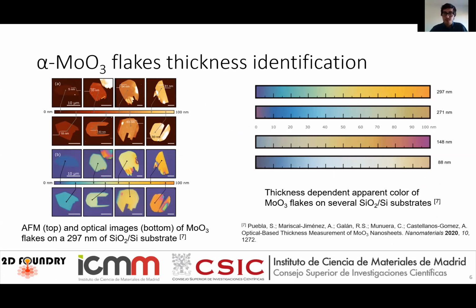We see these experiments as interesting enough to develop some methods to calculate the thickness and to speed up the thickness identification and the symmetry identification of the crystal. For example, we have placed molybdenum trioxide flakes onto a silicon dioxide substrate. In this case, it's 297 nanometers of silicon dioxide, and you can identify the thickness of the flakes with the AFM, and then you can create a color bar which goes from a few nanometers to 100 nanometers of molybdenum trioxide, and it's going to be at different colors.